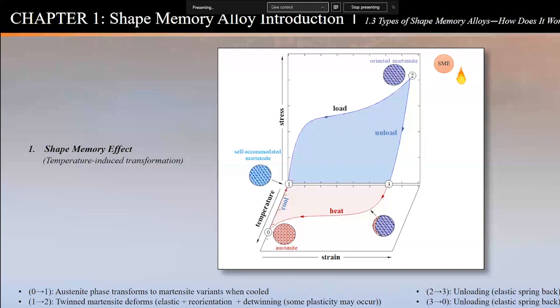If I go from 3 and now I heat this material, I apply heat. Once I apply heat, this material actually recovers. It goes back to 0. And in the process, as these phases are changing, the phase transformation is occurring. It goes from some sort of low symmetry microstructure to high symmetry. I recover all this deformation, just like the metal never was deformed before. So this mechanical deformation is recovered by this heating part of things. And now you're back to zero. So this cycle is repeatable by load, unload, heat, and cool. You can do it all day in a perfect condition.